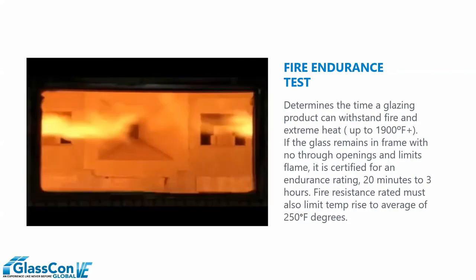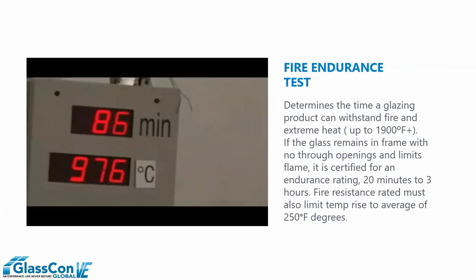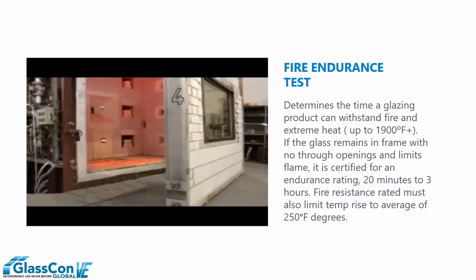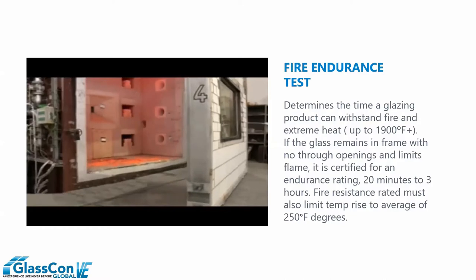The individual administering this test is wearing protective gear because this is fire protective glass. So the amount of energy that's radiating through this glass opening is significant. We can see temperatures at 976 degrees Celsius, which translates to about 1700 to 1800 degrees Fahrenheit. So very unstable environment. Again, we only want to see how long the glass is going to remain in the opening. So at the conclusion of this test, you can see the buck is actually pulled away from the furnace.